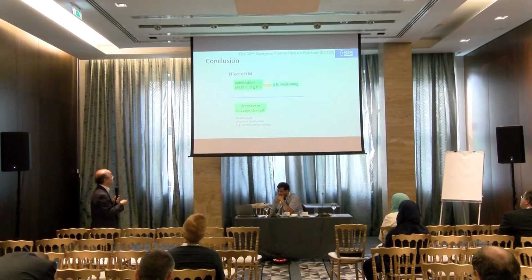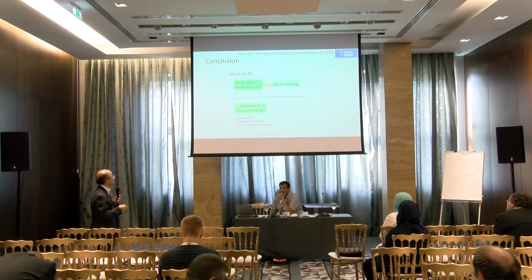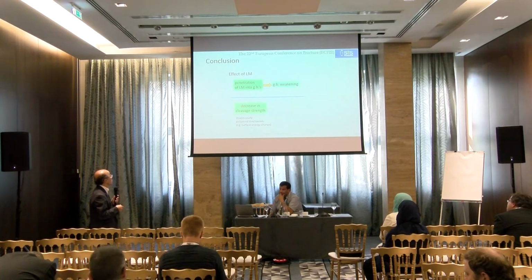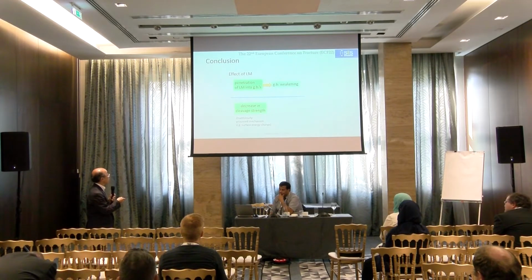From these results, there are two things happening which should be distinguished. One is penetration of liquid gallium into grain boundaries, which makes the grain boundary weak. The other is the decrease in cleavage strength. These are completely different things.